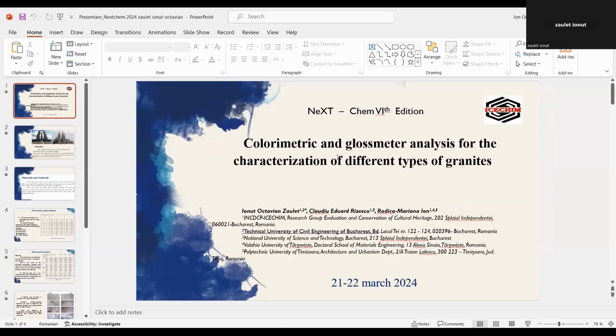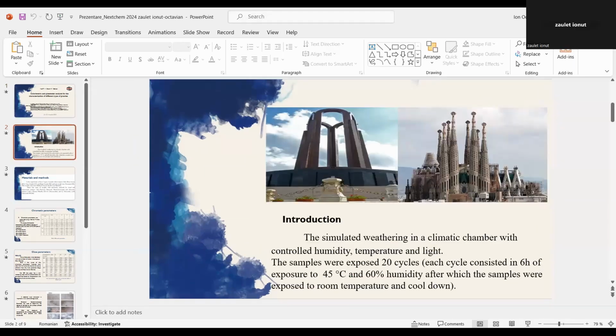Hello, everyone. My name is Ionuț Zaulet, and today I present colorimetric and glossimetric analysis for the characterization of different types of granite. This idea comes from thinking that the Sagrada Familia in Barcelona is made of 3 types of granite. It's very interesting to see how this material behaves over time. In this study, I simulate weathering in a climatic chamber with controlled humidity, temperature, and light. The samples were exposed to 20 cycles, each cycle consisting of 6 hours of exposure at 45 degrees and 60% humidity, after which the samples were exposed to room temperature and cooled down.